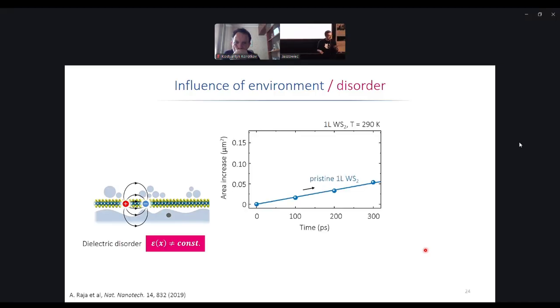You can ask an experienced theoretician. Dielectric screening, yeah, this is epsilon, but what changes when epsilon changes? Binding of the exciton, and now I can go a little bit more advanced. What else changes in terms of electronic transition? Binding of the exciton and band gap, yes? Yeah, so GW, sorry, I'm out of my element, but this is what it does, right? Band gap changes and exciton binding energy changes. So dielectric disorder will impact free carriers, it will impact excitons, it will obviously impact transport, and this is also what is observed.